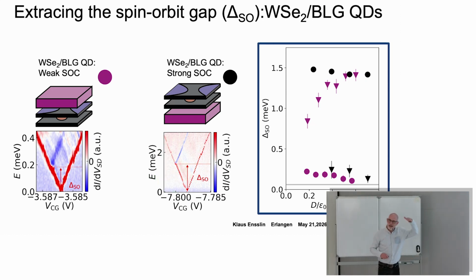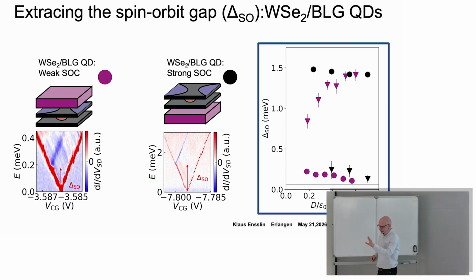So we build a quantum dot in the graphene layer away from the TMD, then we have weak spin-orbit interaction. And just by using our gate voltages, we use exactly the same sample in the same area with the same size, and we build a quantum dot in the graphene layer next to the TMD, and we get this much enhanced spin-orbit, I should say, lifted degeneracy, right?